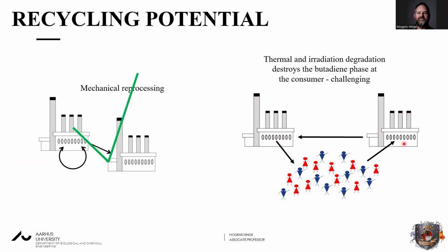Then we return it to some sort of recycling facility. They can maybe sort out or extract the ABS and send it back to the factory. Now, this is pretty challenging because, as I have shown, the butadiene phase is actually disappearing. It's getting destroyed. So it's gone. And the butadiene phase was the part of the material that ensured the high impact resistance. So now that you remove that, you get a more brittle material, and that might not be acceptable when you return it to the factory that is producing the product.